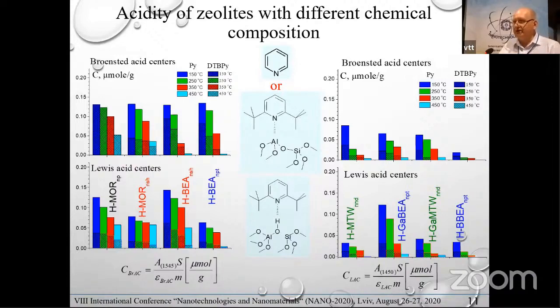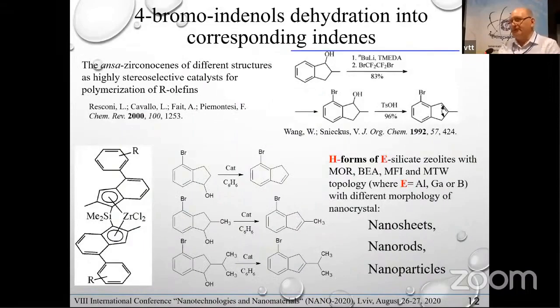For determination of the strength of acid centers as well as the type of such acid centers, different methods can be used. One of these methods is using a spectral probe, for example pyridine molecules, which can determine the type of centers, concentration, and strength of such centers. Of course, the presence of acid centers in zeolites allows us to use such materials as catalysts in different processes, including some processes of fine organic chemistry. As an example, I can show some catalytic activity of similar materials in some fine chemistry reactions.